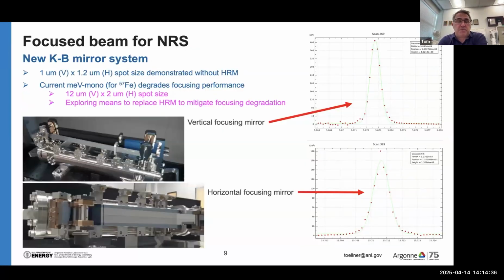For the focused beam, as part of the upgrade, we got a new Kirkpatrick-Baez mirror system. This achieves about a 1 micron spot size, but this is without a high-resolution monochromator. When we introduce the iron high-resolution monochromator, this degrades the focusing performance down to about 12 microns by 2 microns, but most users will be okay with this level of focusing. But we're exploring means to replace this monochromator to mitigate the focusing degradation. This is just due to uncompensated dispersion inside the monochromator.